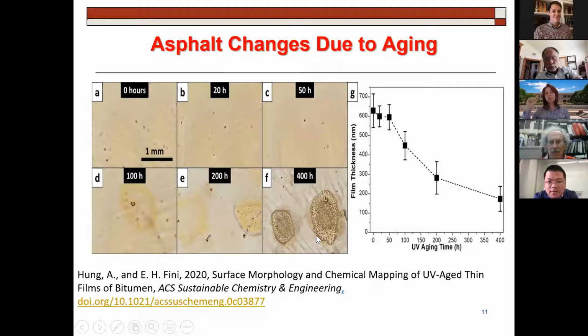And then I measure the film thickness. So I have a bitumen thickness. I'm just aging it, and I keep looking at the thickness. As the aging progresses with hours, it's going down, down, down, down to this. So I'm losing something, right? When the material gets thinner and thinner and thinner, what's happening? Some of the molecules are leaving, right? That's how the thickness is reduced.